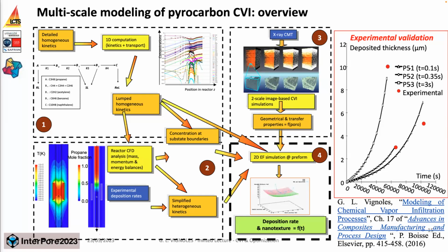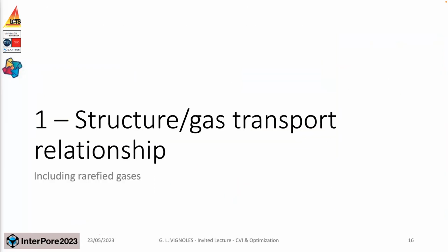But of course, what is important is also to provide all the mass and heat transfer in the porous medium. So the third block is image-based modeling of heat and mass transfer, so that you can have all those properties at several stages of infiltration. And all that is merged together in, for example, finite element simulation of the whole material. And this gives you a distribution of the deposition rate, of the infiltration degree, the degree of pore filling if you want, and also of the precise nature of the material as a function of time that can be compared to actual experiments carried out in our very lab. So we could validate this whole approach. I will give you some more insight in our work on structure to gas transport relationship.